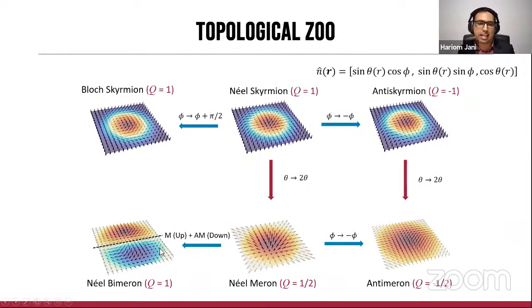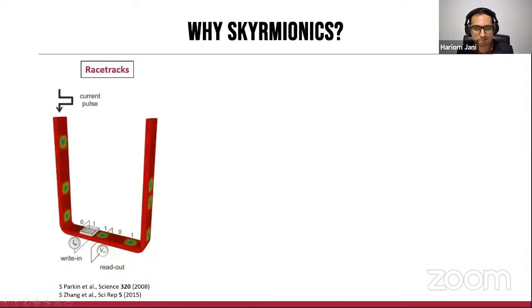Now, an interesting feature of the Néel bimeron is that, of course, you can also obtain this from the skyrmion by simply rotating the spins, and therefore the key difference between the textures below versus above is the background in which they exist. The top ones exist in an out-of-plane background, whereas the ones below exist in an in-plane background, and therefore, depending on the material symmetry that we look at, they would appear in different contexts.